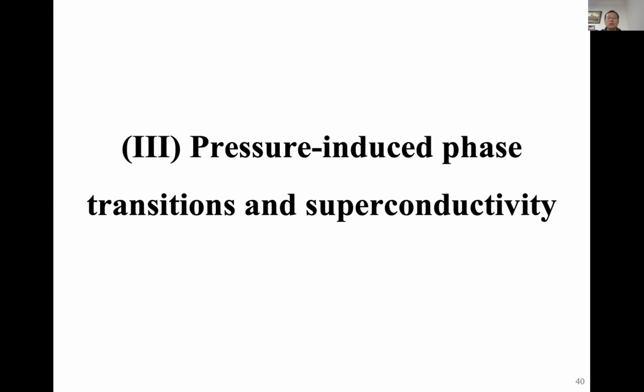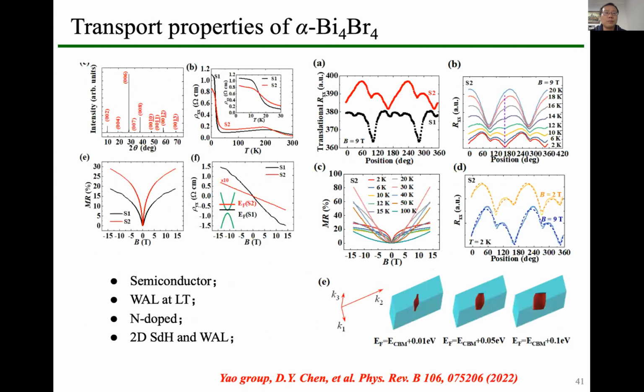So I think I still have some time to show you the pressure-induced phase transition and superconductivity. For this bismuth bromide material, we measured their transport properties, and from this resistance measurement we found that this is a semiconductor, and we can observe weak anti-localization behavior at low temperature. This is an n-doped material, and we can observe very complicated two-dimensional SdH oscillation and weak anti-localization behavior. This behavior might be associated with the topological edge state, but at that time we could not figure out exactly how this is linked together.